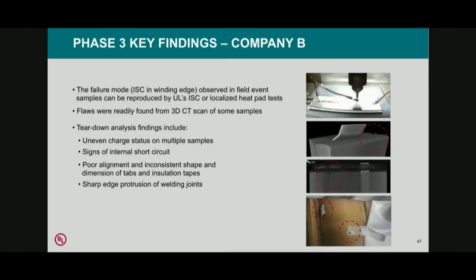The flaws were readily found from 3D CT scan of some of the samples. The teardown analysis showed uneven charge status on multiple samples, signs of internal short circuit, poor alignment and inconsistent shape and dimension of tabs and insulation tapes, and finally, sharp edge of welding joints. For Company B, we found no evidence of device-level incompatibility issues that may have contributed to the failure of the Note 7 in the field.